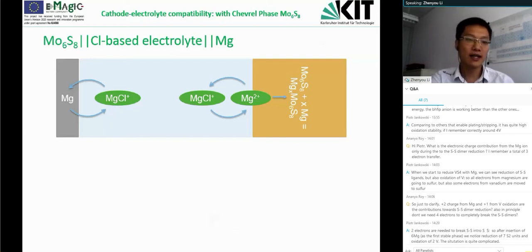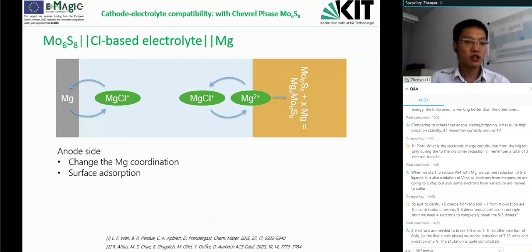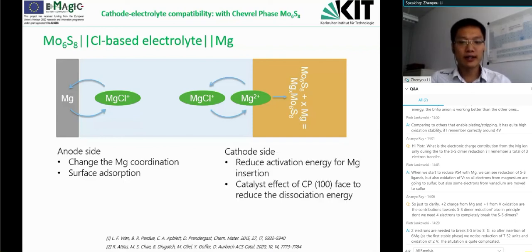So we know that the chlorine ion has a strong affinity to the magnesium, and this will, of course, change the coordination environment of magnesium in a solution. Also, that tends to form the adsorption layer, as Doron mentioned before. So this is kind of protecting the magnesium so that we could, on the one hand, have an efficient plating and stripping, and also ensures a prolonged cycle life. And at the cathode side, the chlorine could reduce the activation energy for magnesium insertion by changing the solvation, and also the Chevrel phase, the surface molybdenum atoms have a certain catalytic effect for this dissociation between magnesium and chlorine. So this further improves the insertion kinetics.